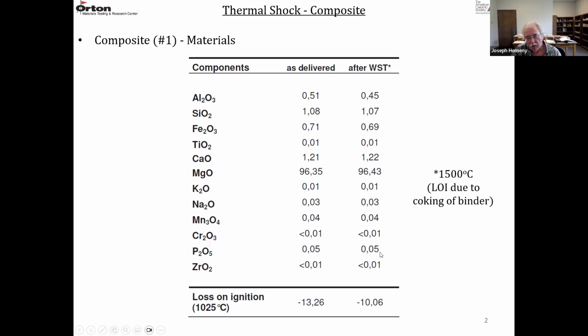The chemistry is the same for the oxide components, but the loss on ignition is a little bit lower, 10%. So testing at 1500 degrees C is basically coking the material. You're pyrolyzing the phenolic resin binder, so there's a little bit less carbon present because of the pyrolysis of the resin. The phenolic resin usually has about a 50% carbon yield, and there's usually 5–6% resin in these materials. So it lost about 3% during the pyrolysis process. My guess is there's 3% amorphous carbon from the phenolic resin and about 7% flake graphite in this material.